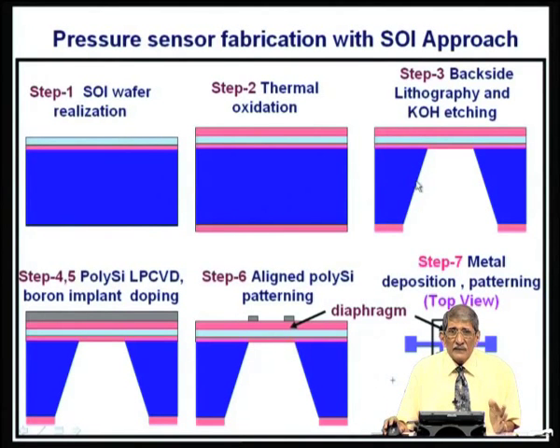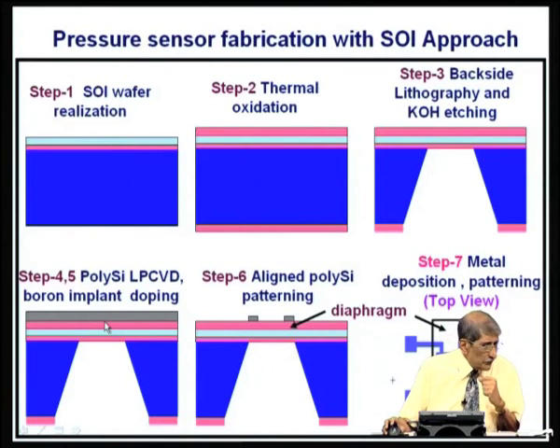Right now, I am showing only how to realize the sensor here. On this oxide, deposit polycrystalline silicon by low pressure chemical vapor deposition, LPCVD. In a furnace where the pressure is something like 200 millitorr, you pass silane and keep the furnace at a temperature of 620 degrees centigrade. The silane decomposes into silicon and hydrogen. That silicon gets deposited on this oxide, and that is polycrystalline.